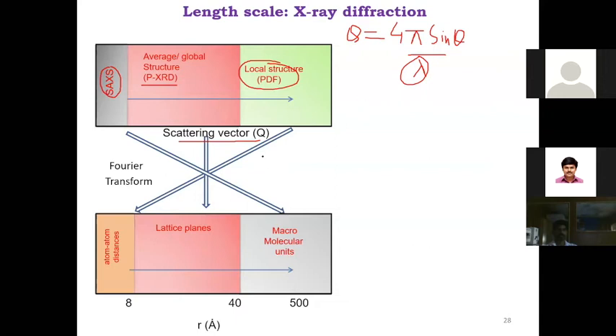I'll give a simple example of gold nanoparticles, in a high concentration gold nanoparticle solid. If we have two gold nanoparticles nearby, the distance between them can be tracked by small angle X-ray scattering, very low angle X-ray. If we Fourier transform it, we get the particle distance, the macromolecular unit. So we can go to distances of about 4 to 5 nanometer, even 10 nanometer.